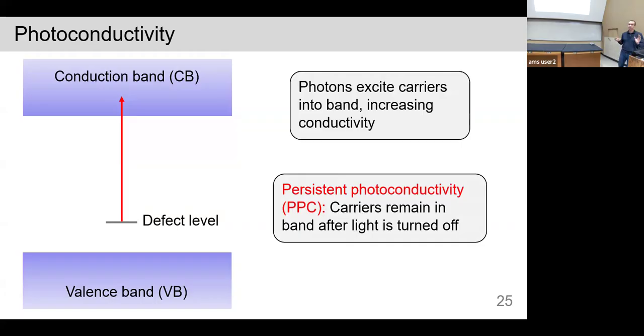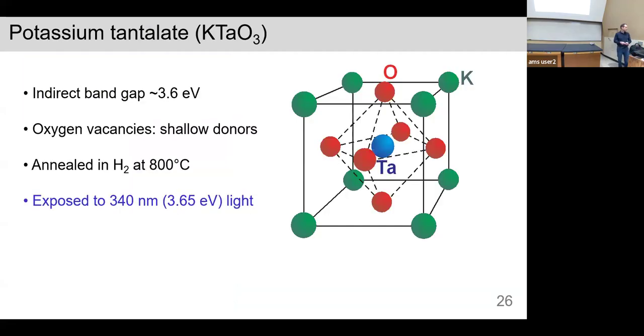Now, persistent photoconductivity, or PPC, is where the carriers remain even after you turn the light off. Sometimes for a few minutes, sometimes for much longer. So my student Macarena has been looking at potassium tantalate. It has a band gap of 3.6 eV, so that's well into the ultraviolet. Oxygen vacancies, missing oxygen atoms, act as shallow donors. And to give it this persistent photoconductivity property, first it's annealed in hydrogen at 800 degrees, and then exposed to light near the band gap, 340 nanometer light. And that results in persistent photoconductivity, as I'll show.